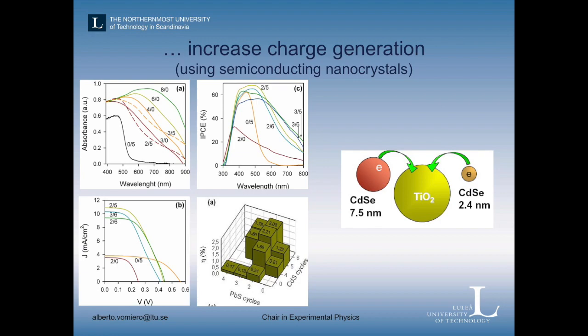So it's not always easy to get these results. And our colleagues working in microscopy were struggling for, let's say, a few months to get these results, but at the end we were very happy of what we were able to demonstrate. So I already told you you can tune the color of these nanoparticles just changing the size, and this is very important because by changing the size somehow you change the ability of these crystals to create the charge, but also to inject the charge from them to the other material who is able to transport the charge.